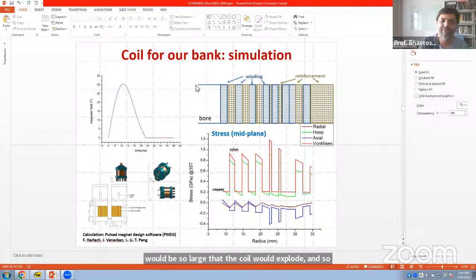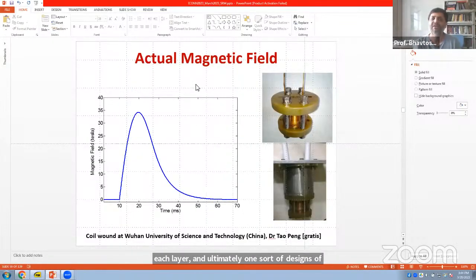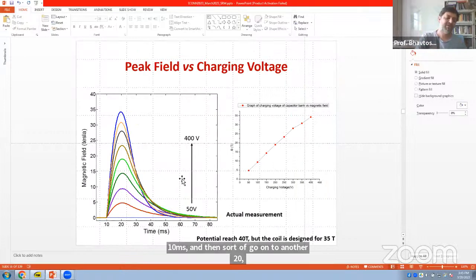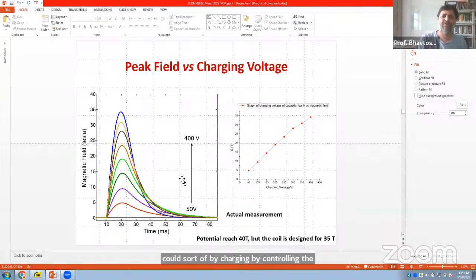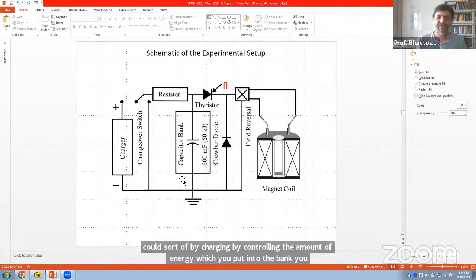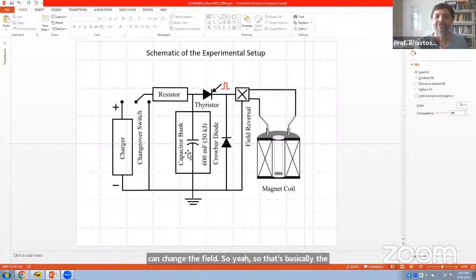So what one does is make a layer of copper, but then reinforce it with a high strength fiber. One calculates the stress in each layer, and ultimately one designs a coil which looks like this, where you have these copper layers which are reinforced. With such a coil one can get a field like this. This is a field in our lab which rises in around 10 milliseconds, and then goes on for another 20 milliseconds. By controlling the amount of energy which you put into the bank, you can change the field. So that's basically the setup: you have the bank of capacitors and some switches which you can close and dump this energy into the coil.